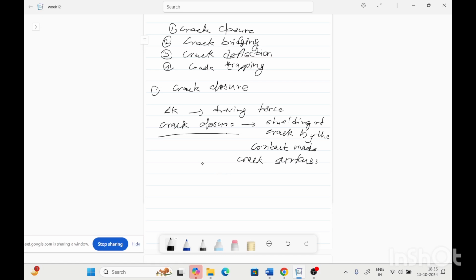And if some asperities form on the crack faces, this is the roughness induced closure. Means if the roughness of the crack surfaces is higher, the crack can close because of this also, roughness induced closure.